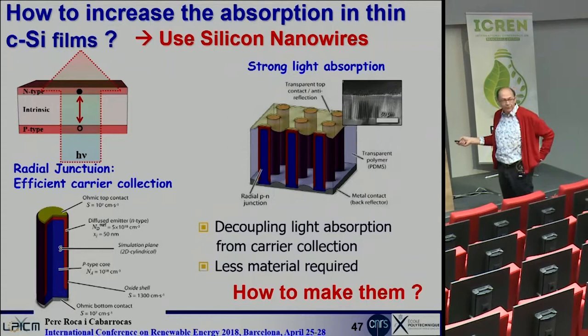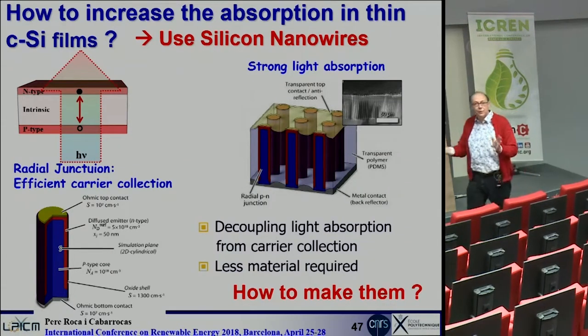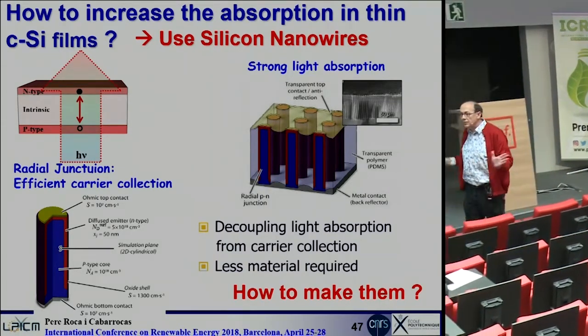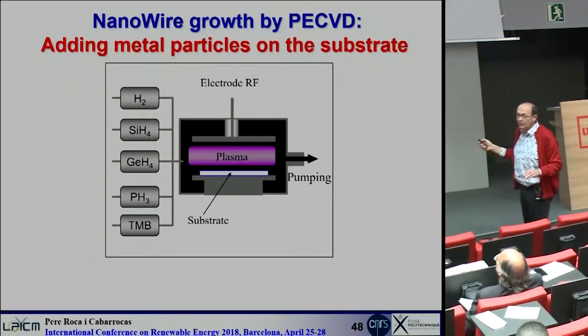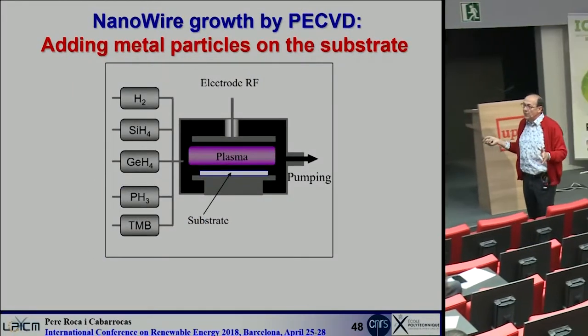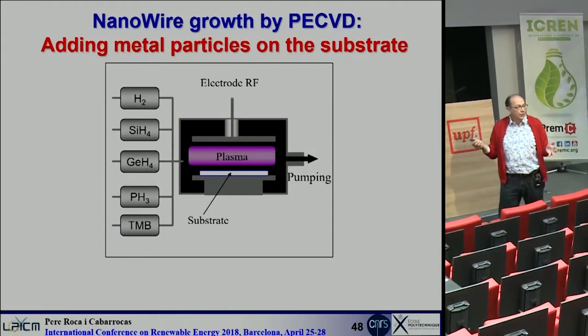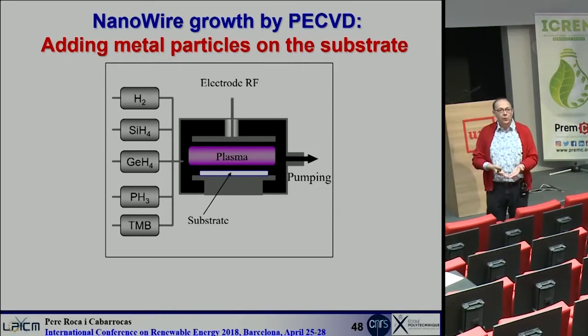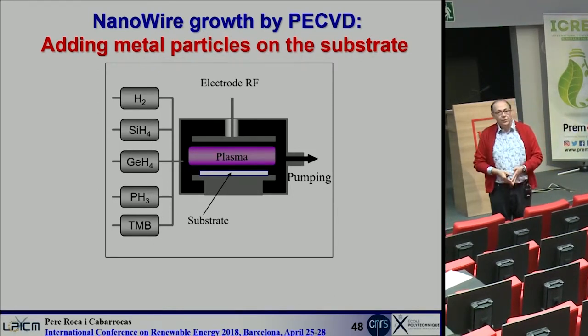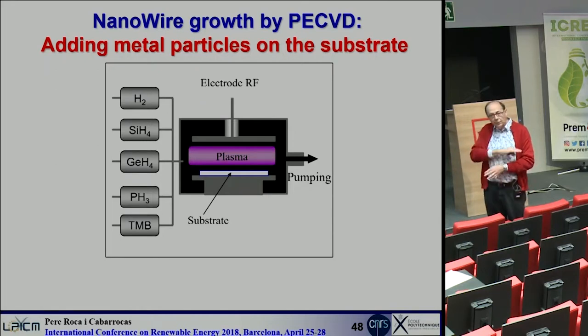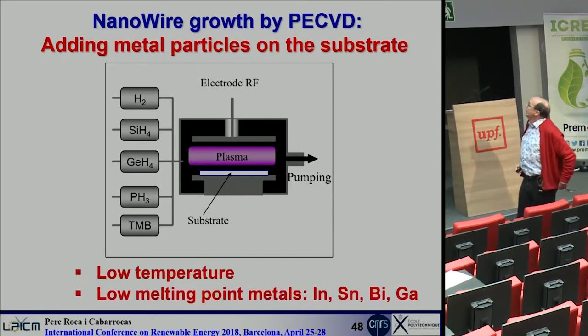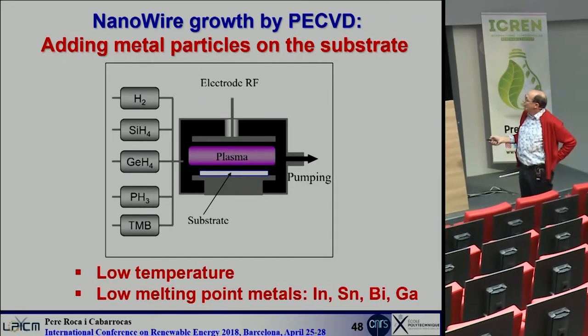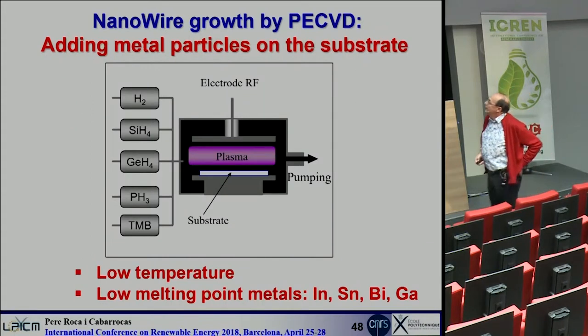Well, you have guessed that I only know how to use a PECVD reactor, so I use a PECVD reactor. It's the same. And what we are going to change now is the substrate. On the substrate, I need something which will promote the growth of the nanowire, the 1D growth. Not planar, 1D. So what we are doing is putting low melting point metals on the substrate: indium, tin, bismuth, gallium.